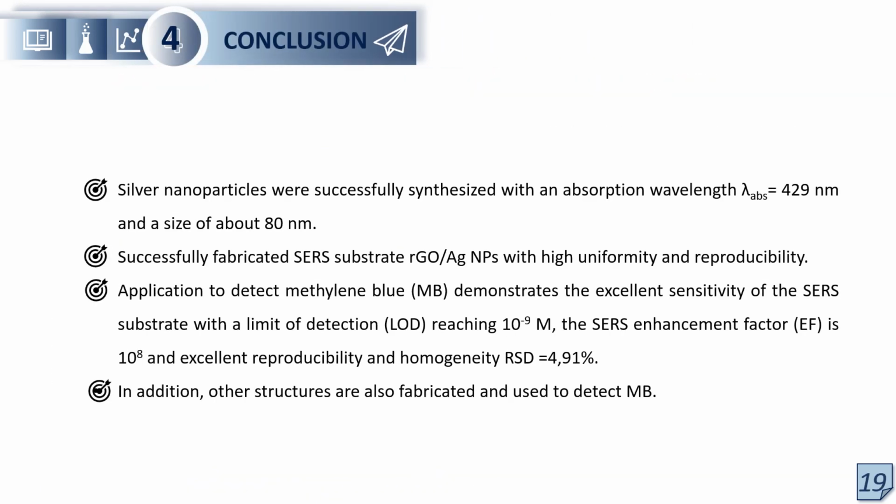In conclusion, we have successfully synthesized silver nanoparticles and RGO and applied them to detect methylene blue, demonstrating the exceptional sensitivity of the substrate with a limit of detection reaching 10 to the power of minus 9 M. The enhancement factor is 10 to the power of 8, with excellent reproducibility and homogeneity of 4.91%.